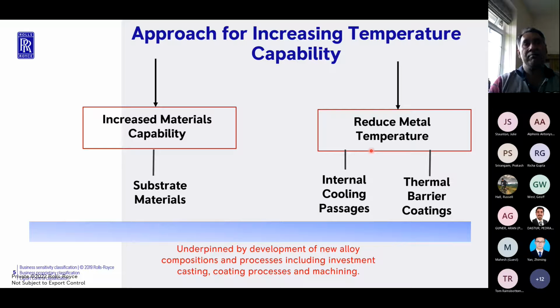Now, you would not have many metals, or at least the common metals that you use, that would be able to survive at those temperatures. I mean, leave alone nickel. So how do you effectively cool the blade? How do you make the temperature of the blade colder, even though it's in contact with a very hot gas? So two very common ways of doing this. One of them is to provide for internal cooling passages within the blade. So you may pass air through different cooling channels within the blade. So effectively, it serves to cool the blade. It takes away the heat. So clearly, you need to have some kind of cooling arrangements within the blade.